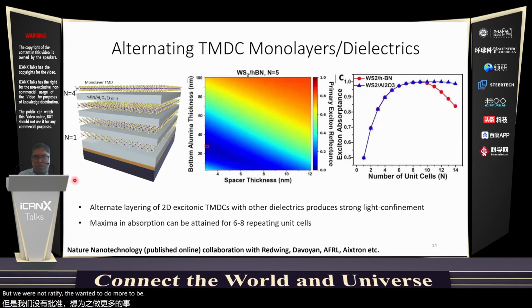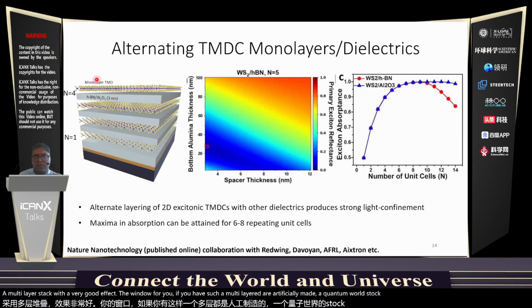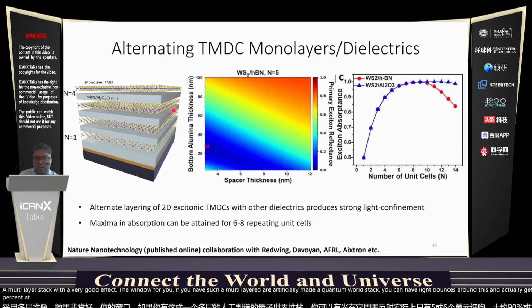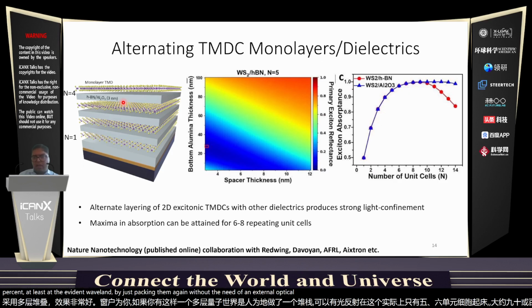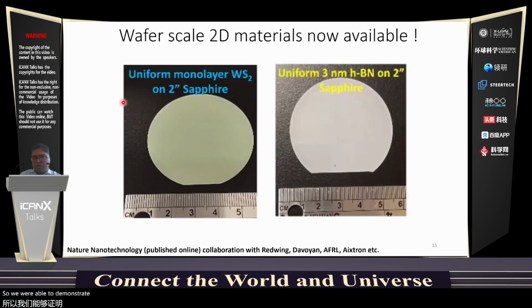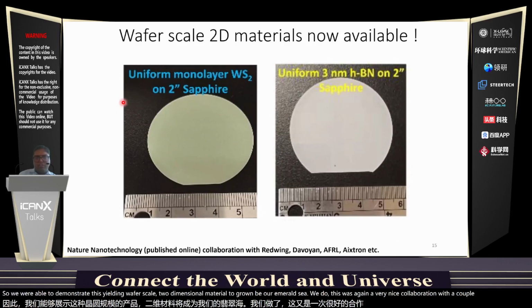So we started looking at multi-layer stacks with varying refractive indices. If you have such a multi-layer or artificially made quantum well stack, you can have light bounce around in this and actually get trapped for just 5 or 6 unit cells at about 90 or 100%, at least at the exciton wavelength, by just stacking them, without the need of any external optical cavity. So we were able to demonstrate this using wafer scale two-dimensional materials grown via MOCVD. This was again a very nice collaboration with a couple of other groups and companies.